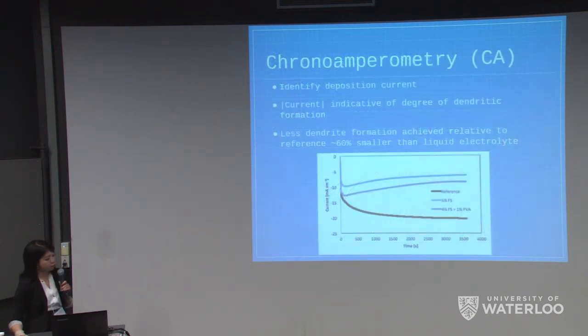CA is an established method to determine whether dendritic formation has occurred on the electrode. An overpotential is applied to force zinc deposition on the working electrode, in our case the zinc electrode, to determine the type of deposition, whether it's dendritic or not. The current density can be plotted against the time to determine whether or not dendrites have formed. The plotted curve will first experience a decrease in the slope as the current stabilizes, but will reach an equilibrium after a certain period of time.